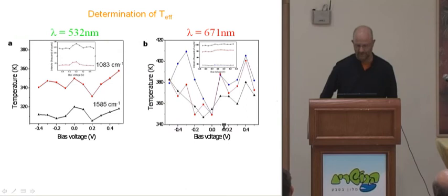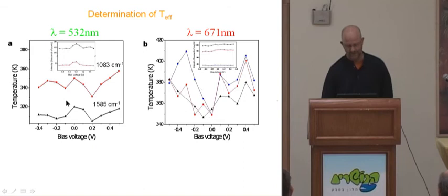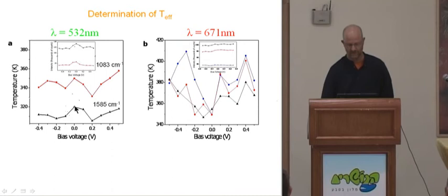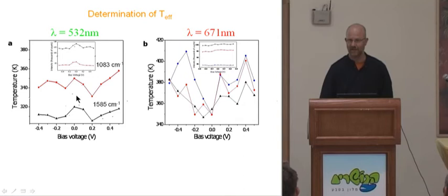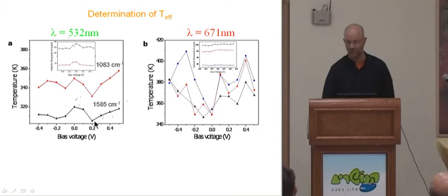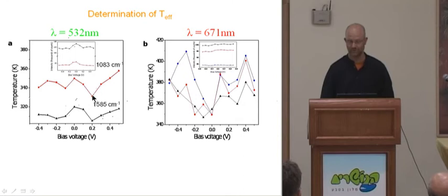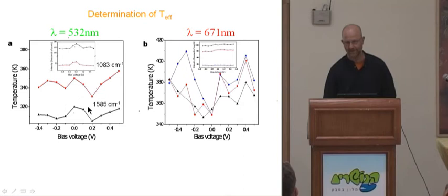Here are results from the same junctions measured with a different wavelength. We see a different behavior: starting at a certain temperature, there is initially cooling taking place and only afterwards heating, observed in two modes. We can partially explain this behavior by a resonance Raman effect, but this also opens the possibility that there are circumstances where tunneling actually cools vibrational modes of molecules. This kind of effect — a molecular Peltier effect — has never been observed before.